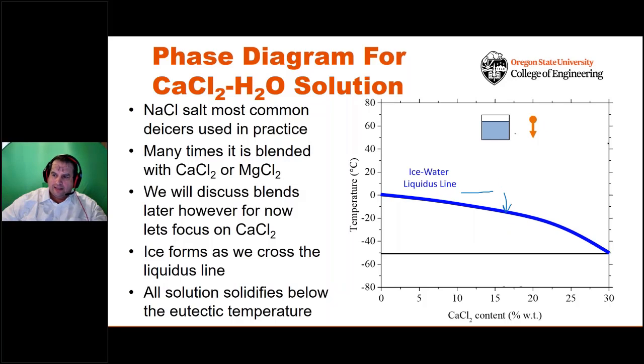So if we're at a high temperature and we have a jar of the salt water, we simply just have a jar of hot salt water. If we start to drop the temperature, the temperature decreases, but it stays as salt water until we cross this blue line. This is commonly known as the liquidus line. And as we start to cross over this line, ice cubes start to precipitate out. Those ice cubes are going to be very, very pure, and the salt solution gets saltier.